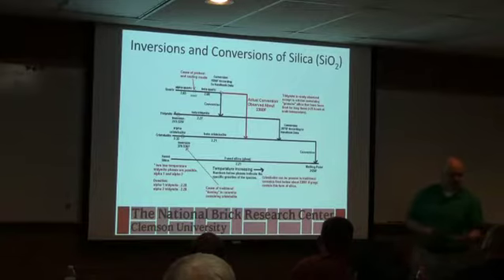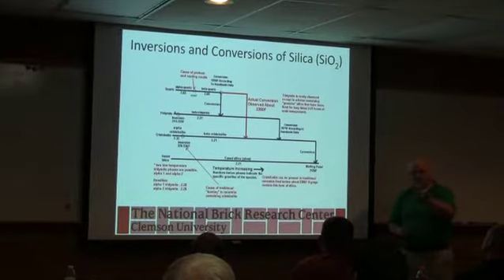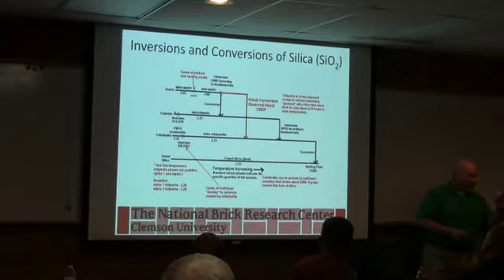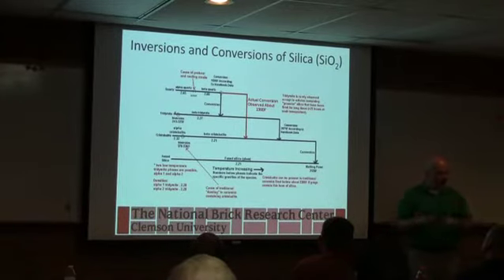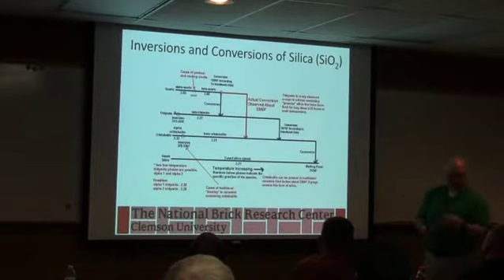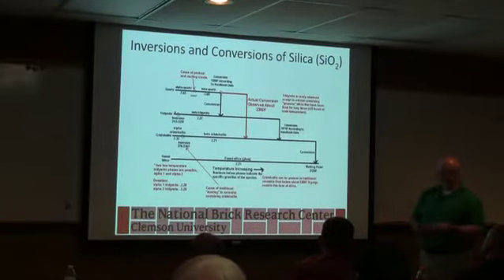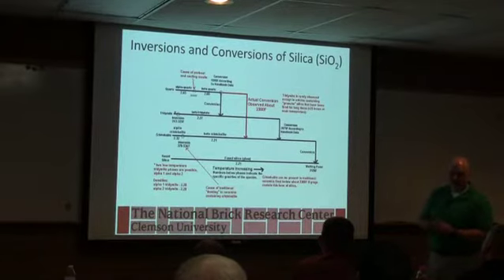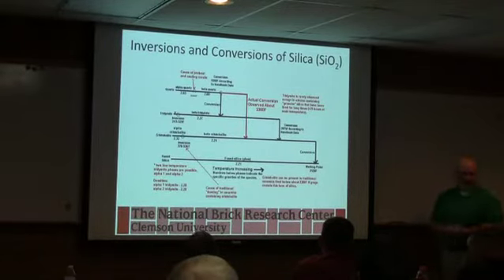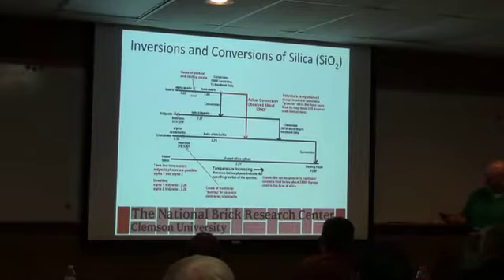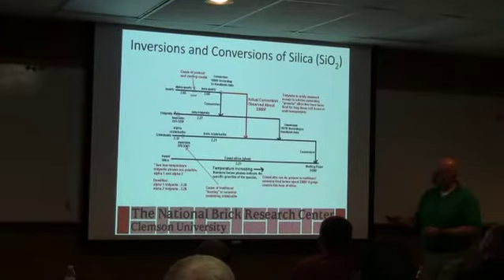I'll show you some pictures later, but you can always pick out the quartz grains in the clay if you look at it under a microscope, because they're shattered. They tear themselves apart. And if your quartz is big, there's a lot of the quartz, or you're going through that change too fast, you do damage to the brick. Okay, so that's something to always consider when you're dealing with that.